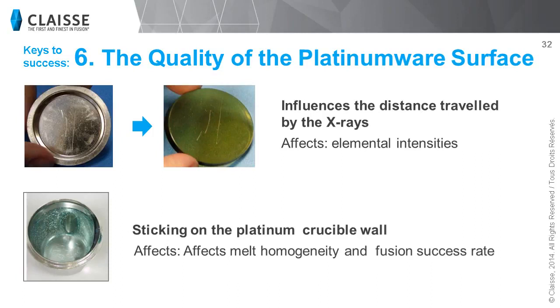Talking about platinum ware, it is also important to remember that the quality of the platinum ware surface also has an impact on the final dissolution and then analytical results. If the internal surface of the platinum crucible is tarnished or damaged, the molten mixture will stick on its sides. The consequences will be less melt homogeneity and an incomplete transfer of the molten mixture from the crucible to the mold or the Teflon beaker.